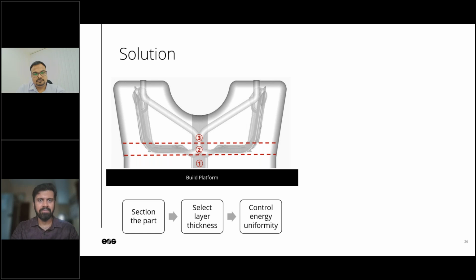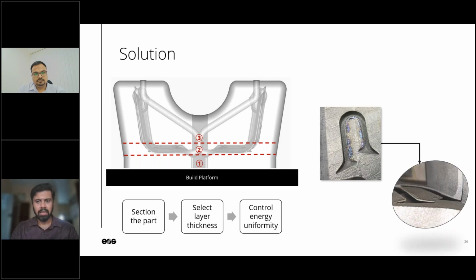And when it comes to a very critical area such as this, where the channel is almost horizontal, we control the energy, also reduce the layer thicknesses, right? For a smaller layer thicknesses, to have the detailed sections, we control the energy such that it is uniform. The energy is uniform such that it does not have any stress concentrations. We typically come across stress concentrations in mechanical loading, but in additive manufacturing, we also have thermal shocks, and that could have the burnt marks. And after we have this, now we see there is not a burnt mark that comes in.